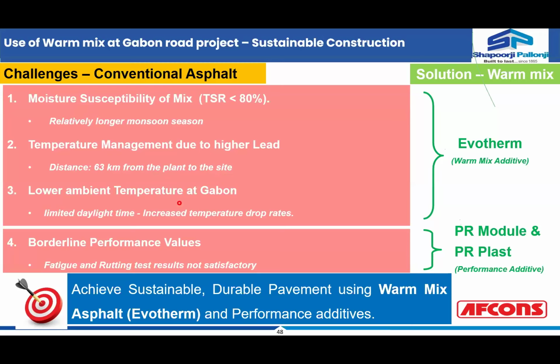And the third one is lower ambient temperatures. When your ambient temperature is low, or when your mix temperature goes below 100, even with less compaction efficiency you will be able to compact a warm mix asphalt as compared to the hot mix asphalt, because in hot mix asphalt the workability of the mix drops once your mix temperature goes below 100. That is the reason why the standard says your rolling temperature should be closed before the mix temperature reaches 100 or 90, depending upon the type of the binder being used in the asphalt mixes.